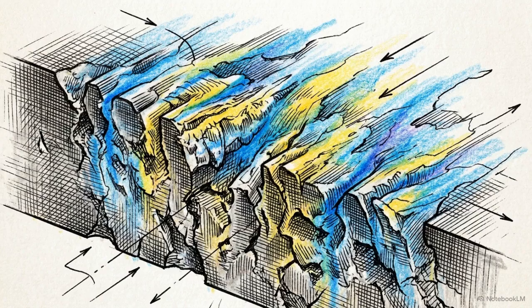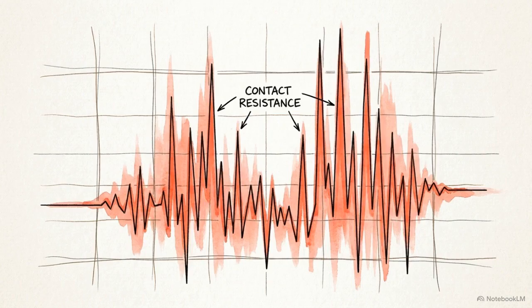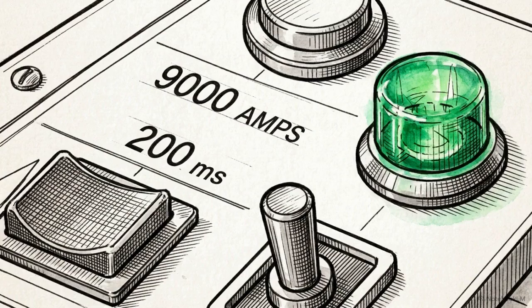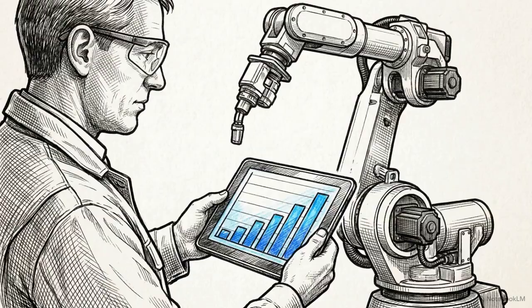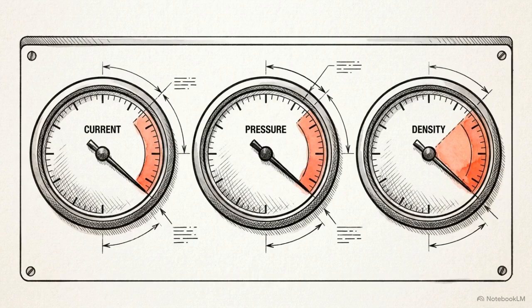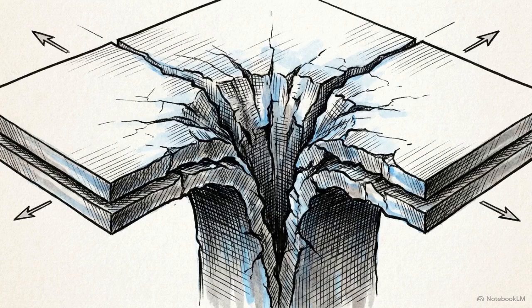This degradation accelerates when welding galvanized steel. The zinc coating melts and chemically alloys with the copper tip. This rapidly degrades the surface, introducing variations in electrical resistance. Trusting a static weld schedule is an operational trap. Continuous manufacturing requires engineers to anticipate this physical degradation and dynamically step up the current to compensate for the continuous loss of density.